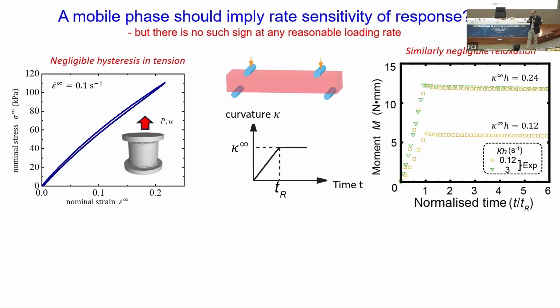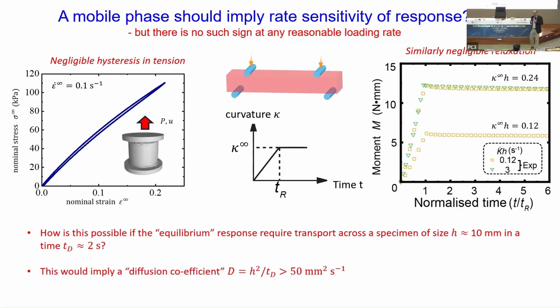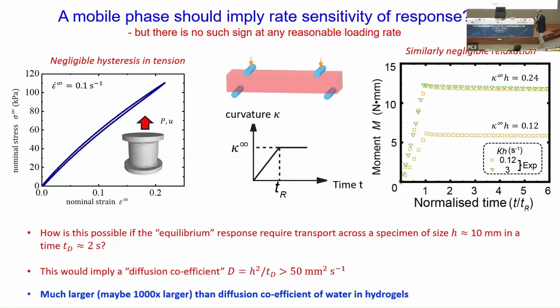If you do a relaxation experiment, there's negligible relaxation. So there is no evidence in this case, over the rates that we are looking at, that you're getting any kind of rate dependence. So how is it that something is moving with no rate dependence? It would basically say that the diffusion rates of this mobile species inside this material are extremely fast. Crazily fast, in fact, 50 times faster than water in a hydrogel or something like that.